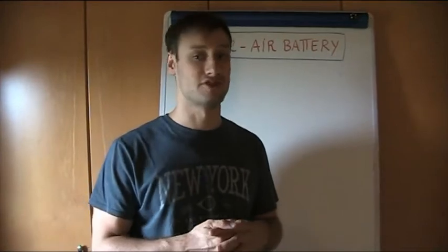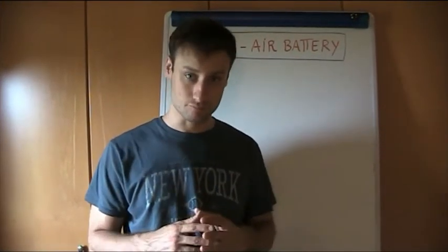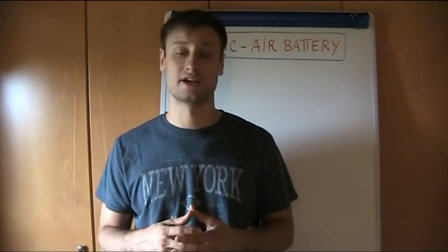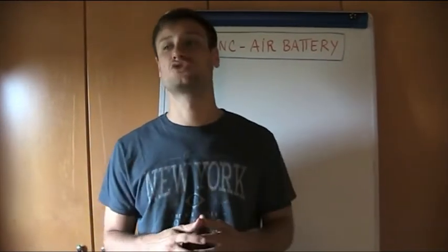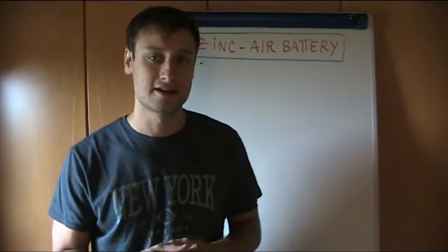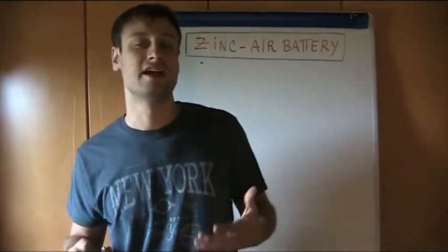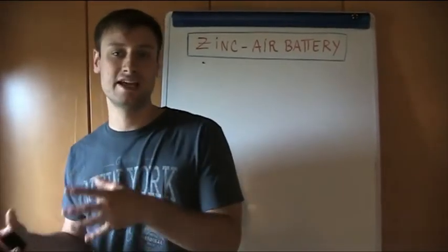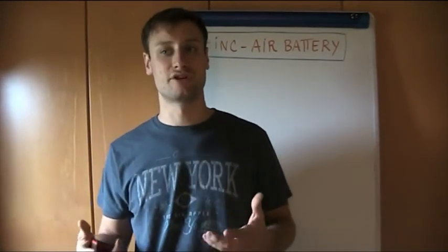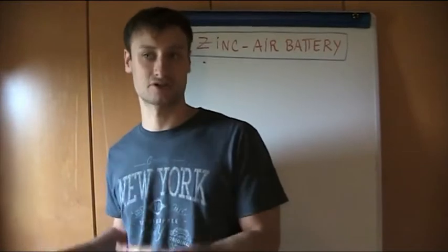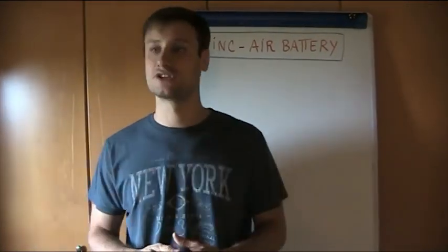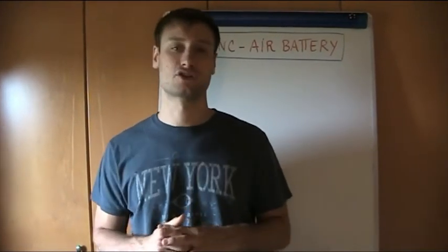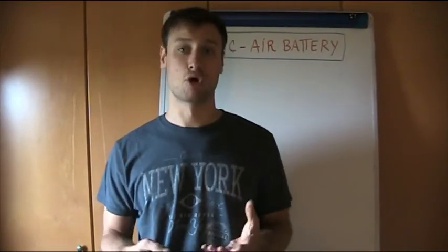Sometimes we also have the possibility to exploit a hybrid zinc-air manganese oxide battery, in which together with the gas diffusion electrode we have some manganese oxide that is able to ensure the working of the battery even in conditions in which oxygen is poorly present. So it's basically a zinc-air battery, but when oxygen is not able to supply sufficient matter to ensure the working of the battery, we have the reduction of the oxide instead of oxygen. Obviously it's important, I don't remember if I stressed this aspect sufficiently, that the catalyst, the point at which the oxygen reduction or eventually the oxygen evolution reactions occur, is often made of cobalt oxide, manganese oxide, or some noble metal.